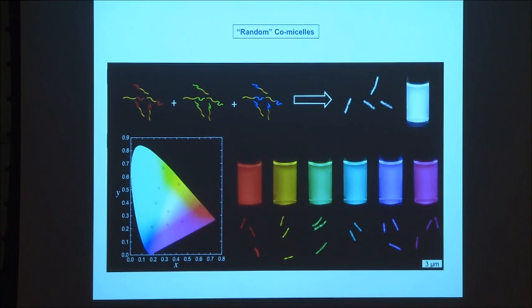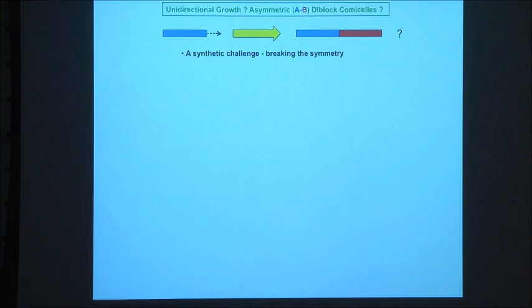Now, one problem in all the self-assembly, or the crystallization-driven self-assembly so far, is that we start with seeds which have 2 faces, so you grow from each end. So every structure you generate has a plane of symmetry in the middle. And so an interesting challenge that we're very interested in is trying to get structures that grow in one direction. Can we break the symmetry?